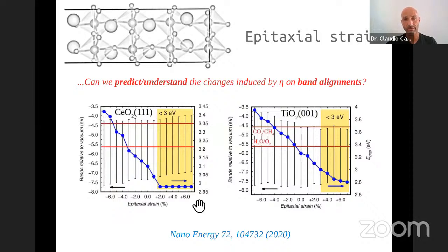However, when it comes to the band alignments, we realized that there was not, or at least we didn't know at the time, any effect that could give us a systematic trend on the band alignments. So for instance, here are two materials for which the band gap evolved in a very similar way, and then you look at the band alignments and actually the evolution is pretty much opposite, right?